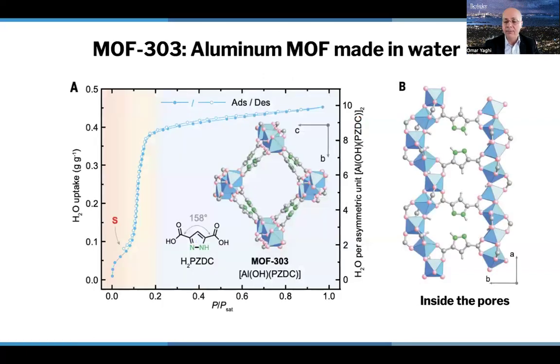So here's the MOF. It's an aluminum pyrazolate MOF. And you see here on the right, the hydrophilic regions where water is going to be binding, and next to them hydrophobic regions, which will reject water. This acceptance and rejection of water allows you to modulate in the pores the binding energy of water and the temperature at which you can remove the water.